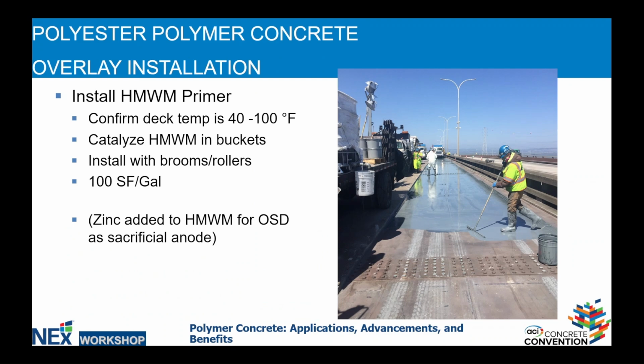During installations, we confirm the deck temperatures with our laser thermometer by just shooting the deck temperature, making sure that we're at least above 40. Now, quite frankly, as I mentioned a moment ago, we could go a little bit colder, but most of the DOT specs will require us to wait until that deck is at least 40.